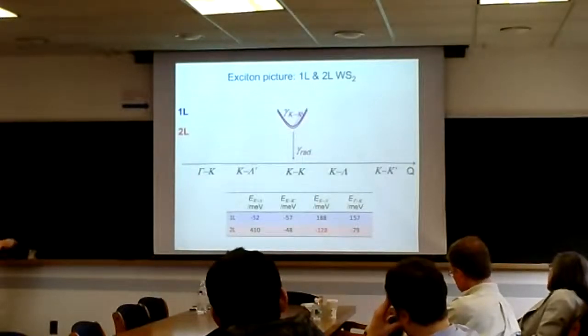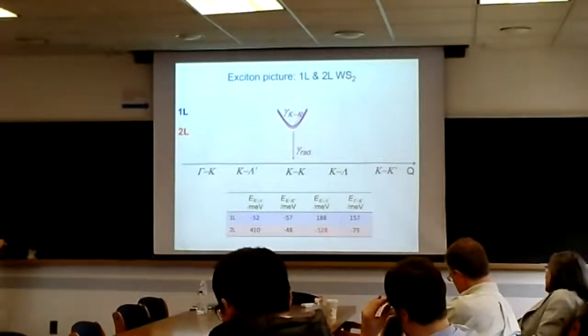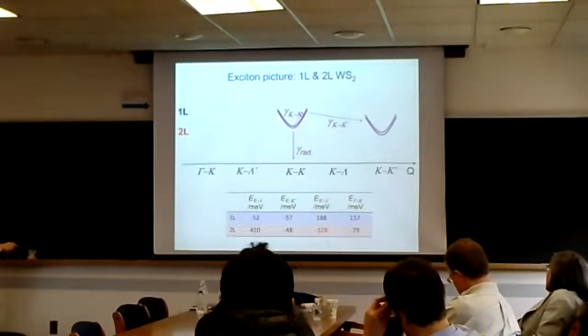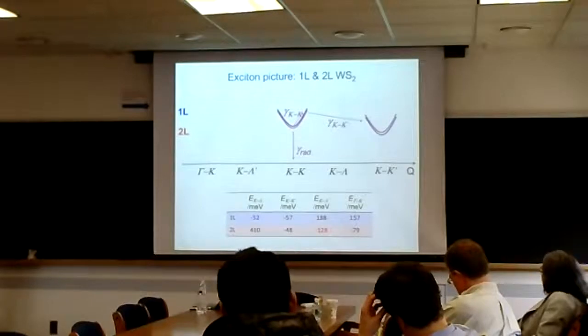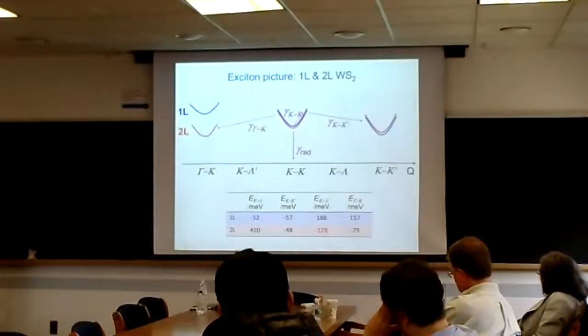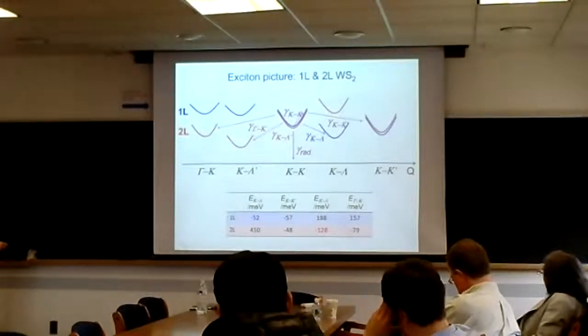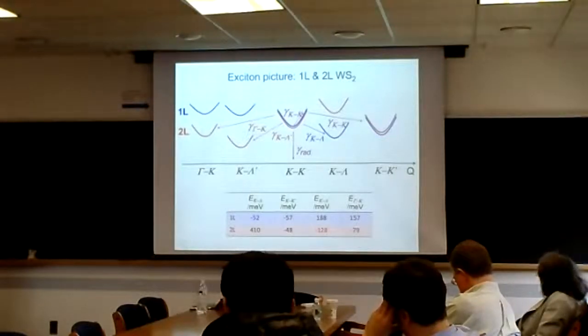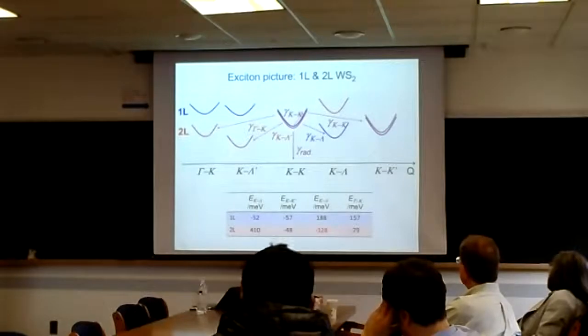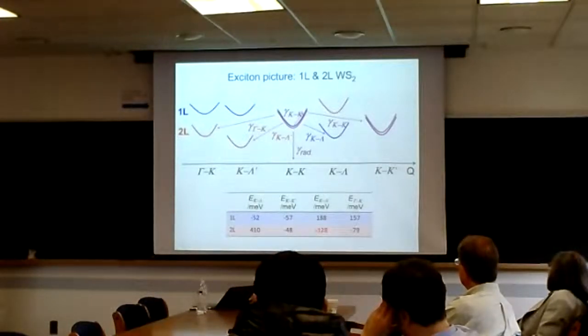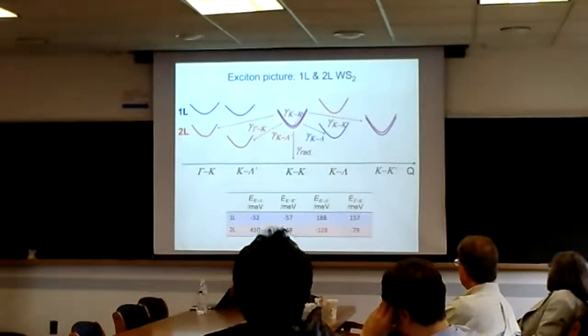So you start with the direct gap at the K point, so you have dephasing processes within the K valley or to K prime. You have this both in the monolayer and the bilayer, which are color-coded in blue and red. And when you go to the bilayer, you definitely have this additional process of the indirect gap. But what the results will show is that these new dark states that form due to increased exciton binding energy at the lambda points contribute the most to this line width increase. So from the 50 meV, most of it actually comes from this and not from the processes that one would have assumed to be more important.